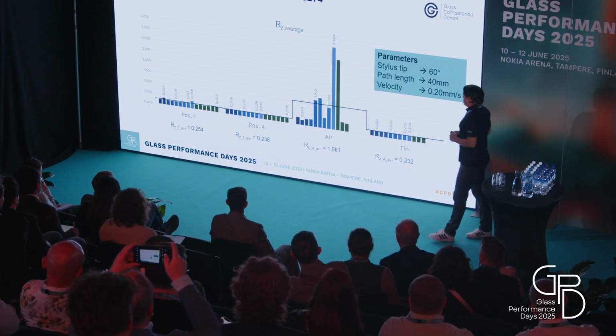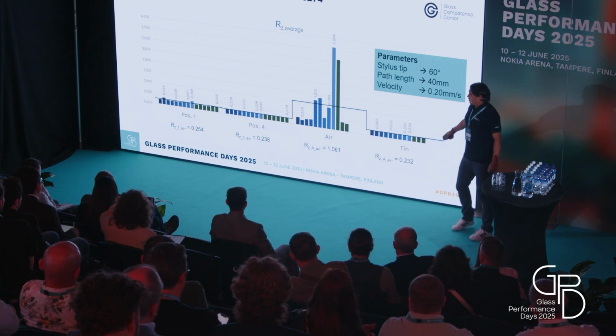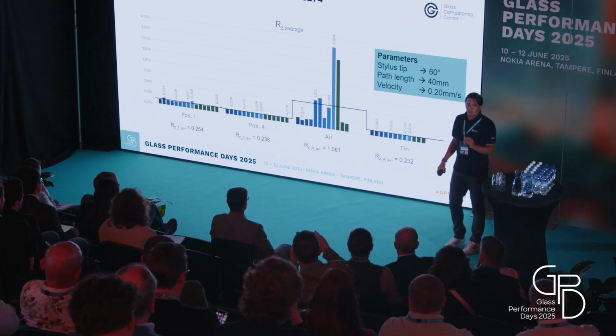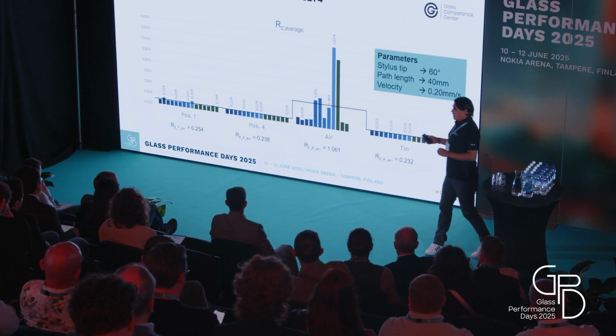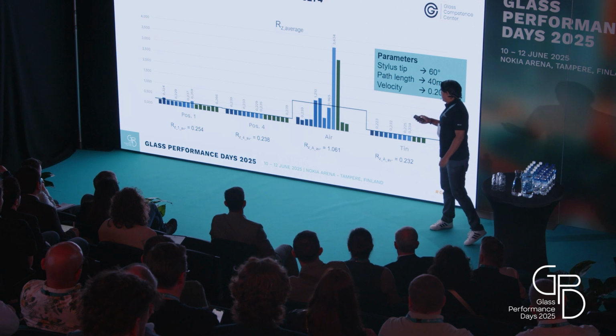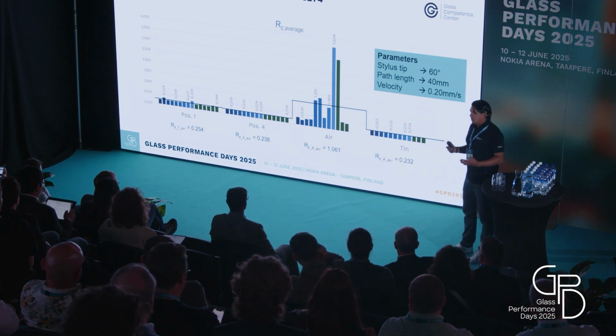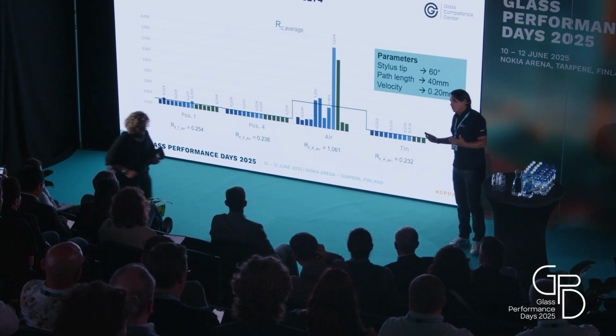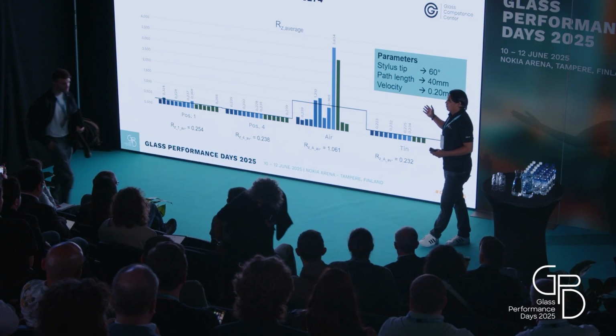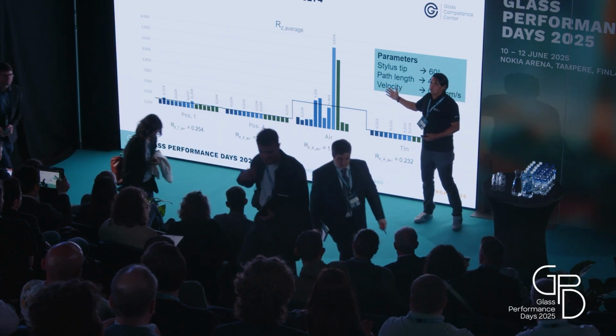Interesting in our results is that from our H glass, position 1 and position 4, as the tin side from our reference glass, had almost the same value, something like 0.23 microns. And on the air side of the reference glass, we had a huge difference, like 5 times more, something around 1 micron. At first I was like, oh, is this going to be a big influence? Should I not test these samples? But actually, it's a good evaluation, in my opinion, because now I can compare if the roughness plays a role.